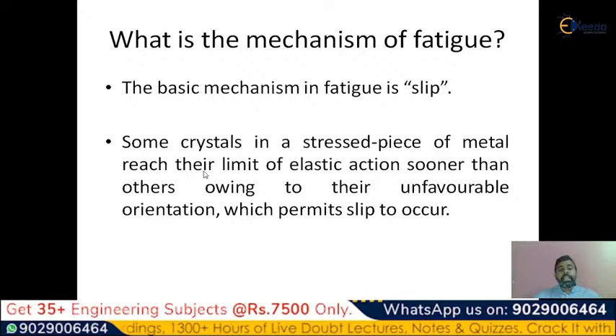Some crystals in a stressed piece of metal reach their limit of elastic action sooner than others owing to their unfavorable orientation, which permits slip to occur. So whenever slip is observed in the material, it indicates deformation, and the fatigue crack is going to be observed. What do you have to do here? We cannot avoid slip. I repeat, we cannot avoid slip. We can reduce the slip. So we have to take care of the measurements and the design considerations so that the slip can be reduced. That is the entire mechanism of why fatigue happens in the material.